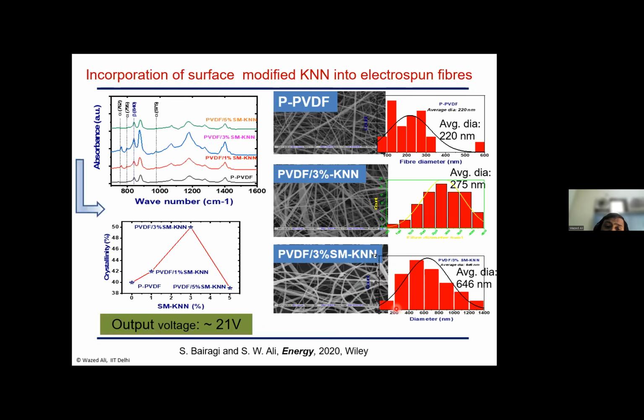Similarly, we have surface modified KNN, as I mentioned, which has also been incorporated in the electrospun fiber. And because of the surface modification, there is more proper distribution, more interaction with the polymeric chain of PVDF, more formation of the beta structure of the PVDF, and even there is an improvement in the voltage generation, at the level of 21. Average voltage I'm reporting, that is 21 volts.